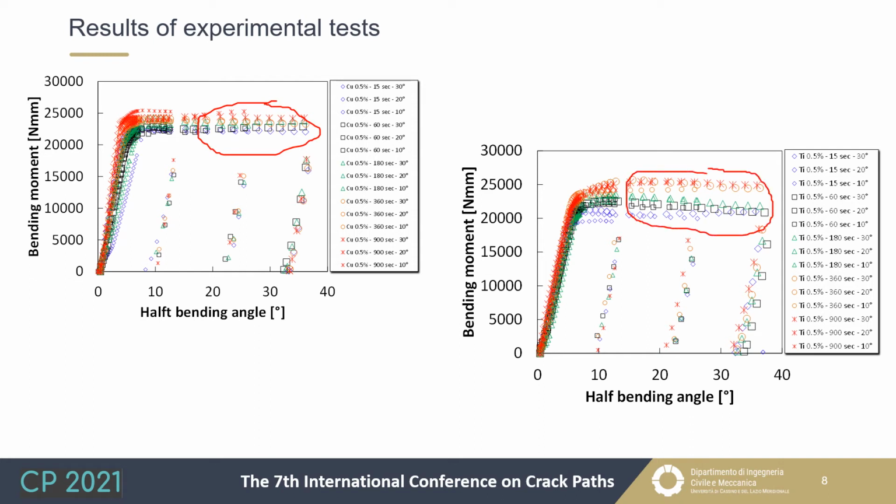Here you can see that the titanium coatings are characterized by lower resistance in terms of bending moment than the specimen characterized by 0.5% of copper. The behavior of the other zinc baths is similar to this, because the phases are always the same.